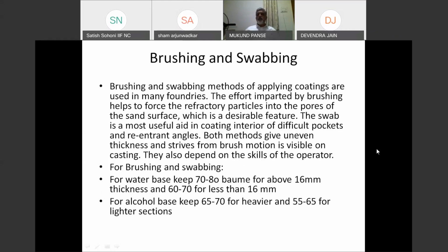The disadvantage is the force applied while brushing. There is certain force applied, so there is sufficient force to push the small refractory particles into the pores between the sand grains. The method gives uneven thickness, and the stripes of the brush or swab are visible on the casting surface, especially in wall and other castings where aesthetic values are important. They don't allow these brush stripes or brush marks.